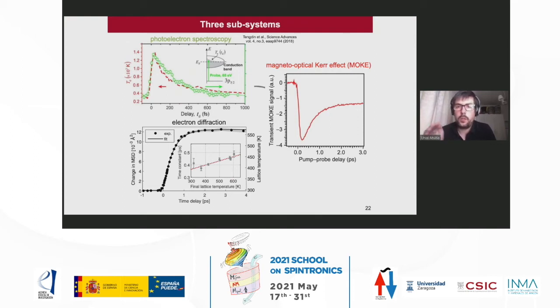If you look at the dynamics of the electrons, you see that this decay of the transient MOKE signal is similar to the increase of the electron temperature. Then in the transient MOKE signal, the magnetization, there is a recovery that also corresponds partially to the decay of the electron temperature in the electron system.